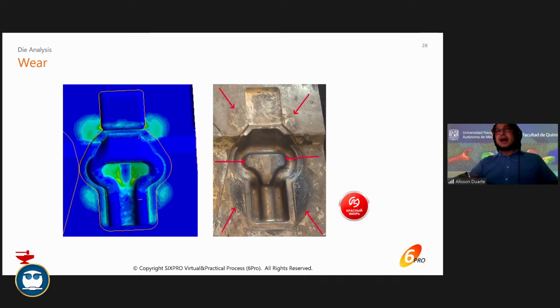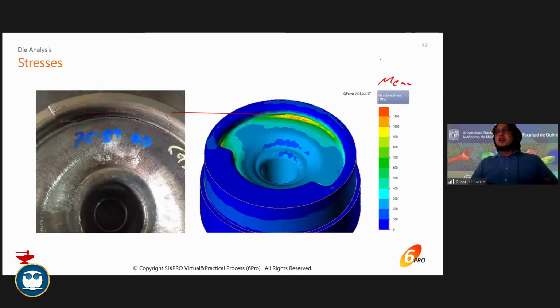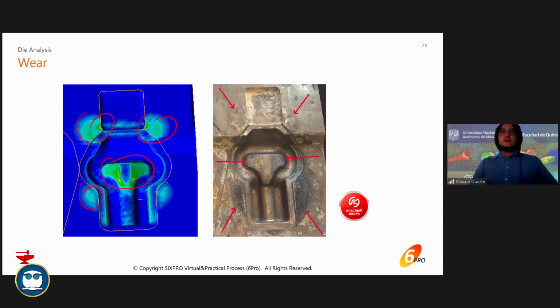Second, I didn't say that, but mean stress is also important. So you understand if it's too positive or too negative, or too tensile or too compressive, it's important. Wear, as you can see here, where predicted areas with wear prediction, and when you go in the practice, you can see here very, very weird areas, you know. So it's important to analyze also wear, because you need also to get to a point when you can predict the amount of parts you can forge with that die, because the tooling is very expensive. So it's important to have this dimension of how many blows or how many parts I can forge with this tooling. So it's economically, money is really important.